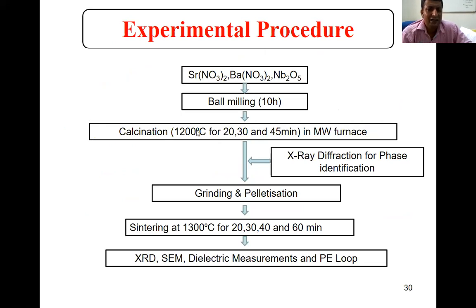And similarly here, of course, we again chose high calcination and sintering temperatures. The reason remains the same. We processed the same system via conventional heating also, and there we optimized the calcination and sintering temperatures, 1200, 1300. So what we did, we played with the calcination time durations and the sintering time durations.